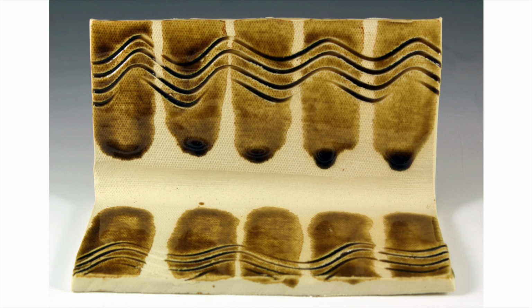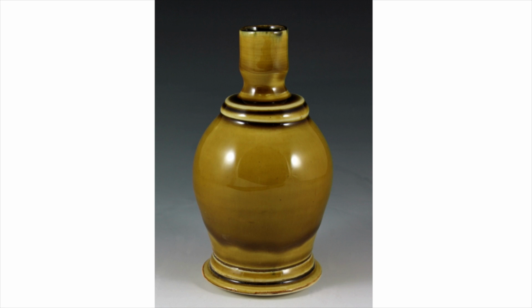In this test, to lower the melting temperature of the common amber celadon glaze, which is a cone 10 glaze, to cone 6, I first substituted nepheline syenite for the Custer feldspar, and then I added Gerstley borate in 5% increments. I then chose the middle stripe with the 10% addition of Gerstley borate for that amber celadon glaze. And this is the bottle.